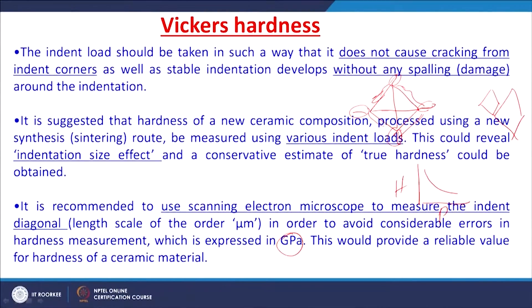Use the scanning electron microscope to measure the indent diagonals precisely. Vickers indentation shall be done at a load where it does not cause cracking from the indent corners and shall not produce spalling around the indentation. Or measurements must be taken at various indent loads so that it could reveal the indentation size effect. It is better to use the SEM than the optical microscope to precisely measure the diagonal length, which is generally in the order of micron-meters.